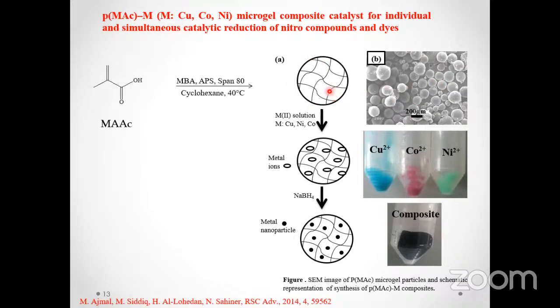So these hydrogels were used as reactors for the synthesis of copper, cobalt, and nickel nanoparticles. In the first step, the precursors of these metal nanoparticles, which are of course their metal ions, were loaded in the hydrogel networks.